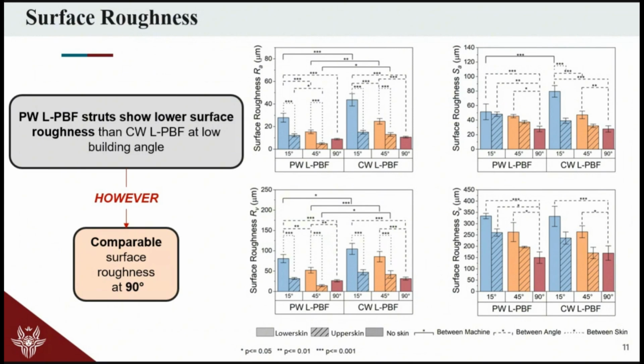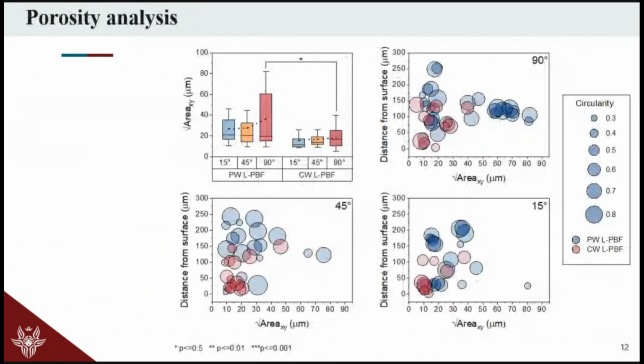So the other logical step is to go through the porosity analysis. Porosity analysis has been done basically cross-sectioning the specimens, several numbers of specimens, at different height of the gauge length in the Z direction, and considering then the Murakami area parameter on the XY direction, and considering the distance from surface and the circularity of the pores, we can see that in the case of pulsed wave laser powder bed fusion, there is a higher tendency for the 90 degrees in particular to have a location of potentially critical pores